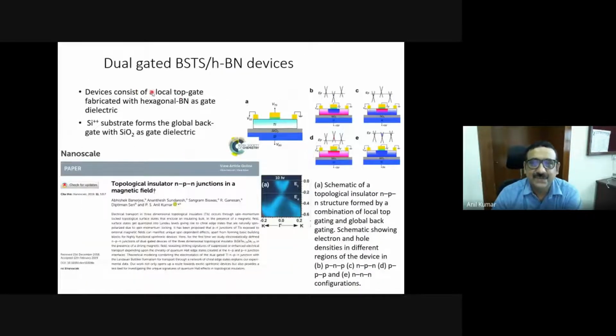Look at here. What we did was we made this kind of device. If you apply a proper voltage here, I can make this region an n-type region. And if I apply a minus 15 volt here, I can make it into a p-type region. So now I have a PNP junction. Similarly, by changing the voltages, I can have an NPN junction. Or I can put the voltages such that I make the entire material p-type, or the entire material n-type.